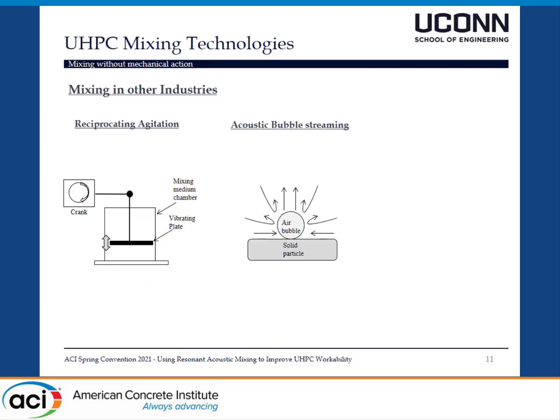Another type of mixer that's used is acoustic bubble streaming. In this type of mixer, you have some solid particle, and around the particle are some air bubbles. Once again, you subject the mixing container to an acoustic wave such that the frequency of this wave matches the frequency at which the air bubbles vibrate. So the vibration of the air bubbles is what mixes the particles together.